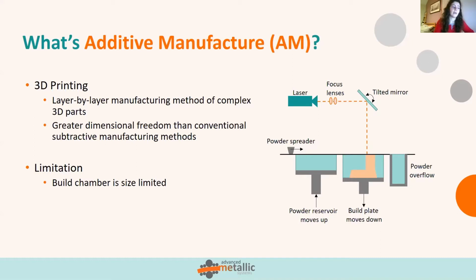Essentially what happens is the powder reservoir moves up as the build plate moves down. The powder spreader then doses the build plate with powder, and then the laser fires selectively on the areas where parts are being produced. The laser causes rapid melting and resolidification of the powder, and this creates a solid part.